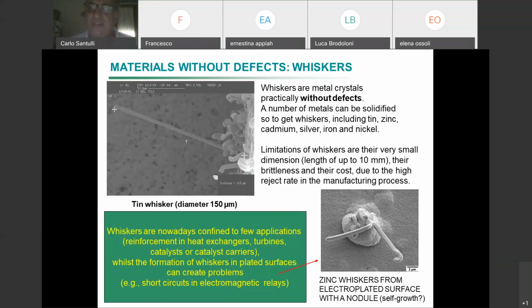They tend to self-grow over the structure by the application of a force, because there is always a force applied to the electroplating, because remember that the plating, the coverage, doesn't deform at the same speed and with the same characteristics as what is below, the main material, the bulk of the material. What happens is that in practice, some whiskers develop which represent a problem.